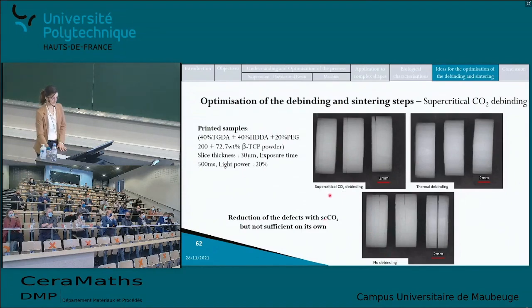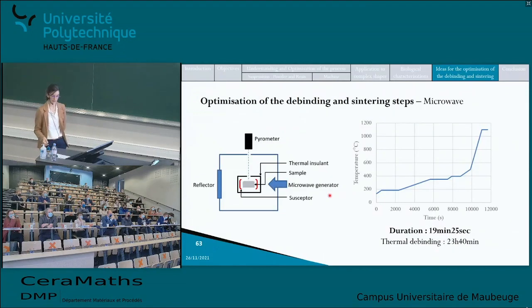So basically the sample is placed inside a microwave generator, and this microwave enables a volumetric heating of the sample that can reduce the appearance of defects during the debinding and sintering step. And it was possible to implement a cycle of a duration of 19 minutes and 25 seconds, which could enable us to gain a lot of time in the production of these parts.